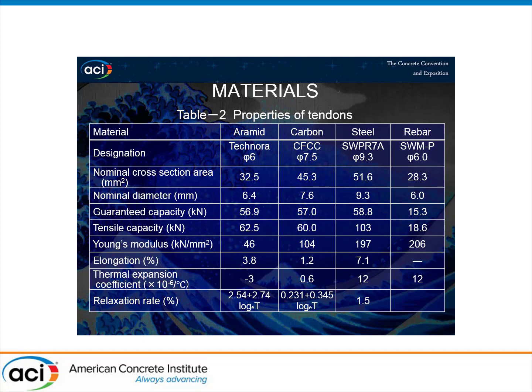This table shows the properties of the materials used as tendons. The aramid FRP is Technora, and the carbon FRP is CFCC. In this table, the Young's modulus ratio is 1 to 2 to 4 for aramid, carbon, and steel. The thermal expansion coefficient of FRP is about 0 or even negative.